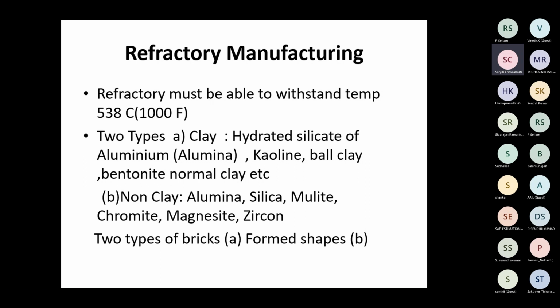By crushing the minerals. Before crushing, sometimes we have to calcine it: manganese carbonate into manganese oxide, magnesium carbonate to magnesium oxide, calcium carbonate to calcium oxide. So you have to calcine it. There we have a calcination furnace. For the calcination process, normally these furnaces are rotary furnaces.